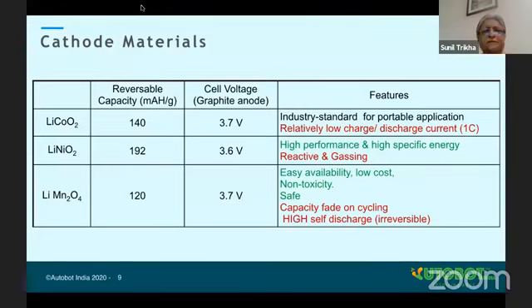These are the different cathode materials used. The most commonly used material was lithium cobalt oxide. Then they tried lithium nickel oxide. Lithium nickel oxide has the advantage that it has much more energy, but it is not as safe as lithium cobalt oxide. The other material which was quite promising was lithium manganese oxide. The advantage of this is that it is a very cheap material. It's a very safe material, but the problem is it doesn't have a good cycle life. So life fades with time.